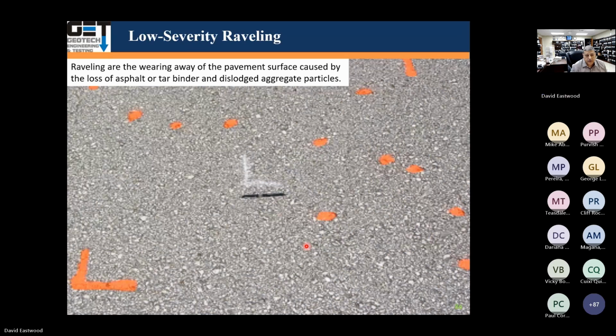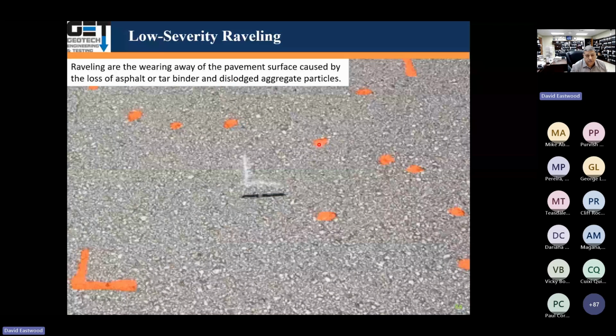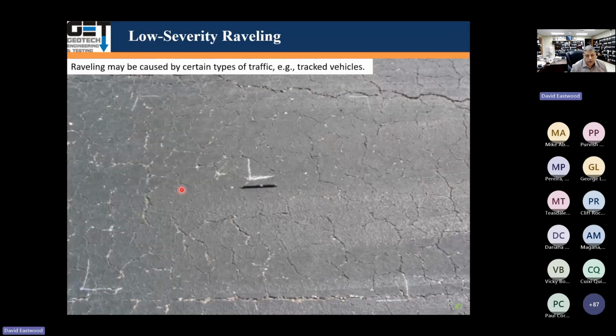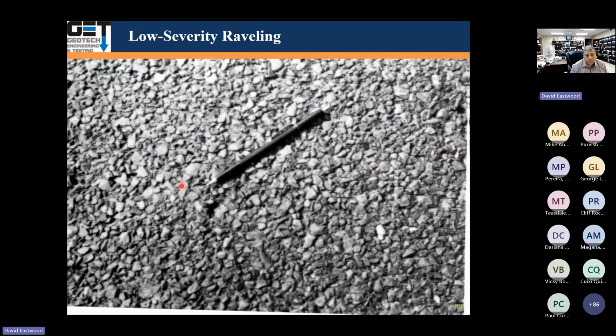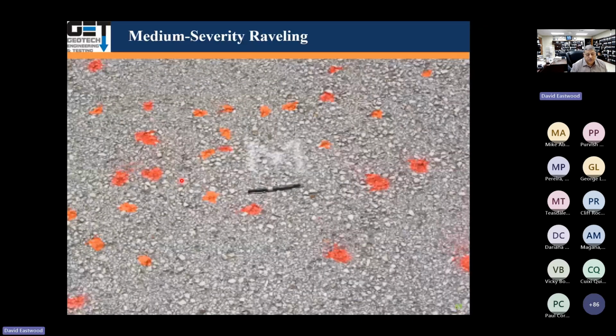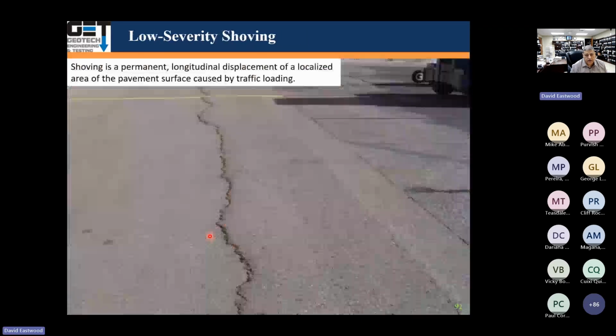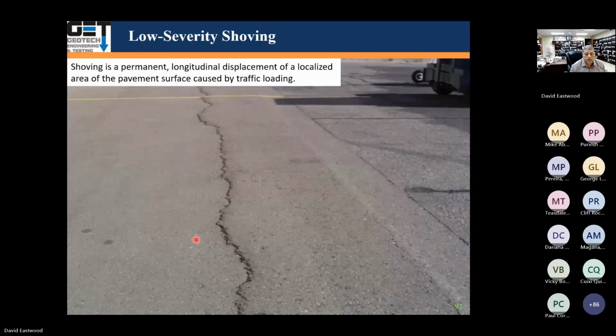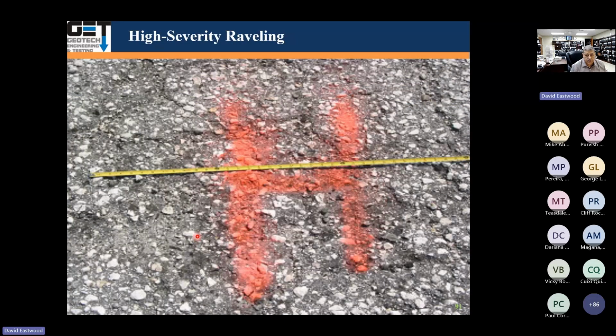Raveling. Raveling is basically when the aggregates are coming off the concrete mix, because of the loss of the binder, asphalt binder. You can see a low severity by traffic, medium severity, and high severity raveling.